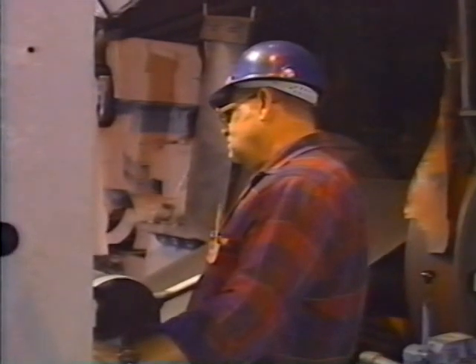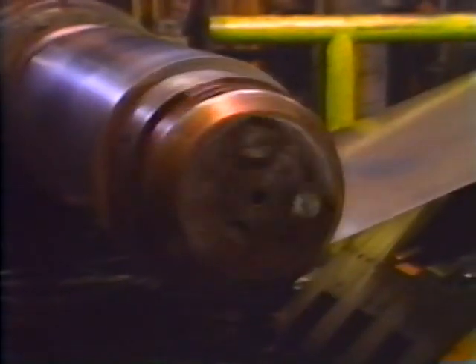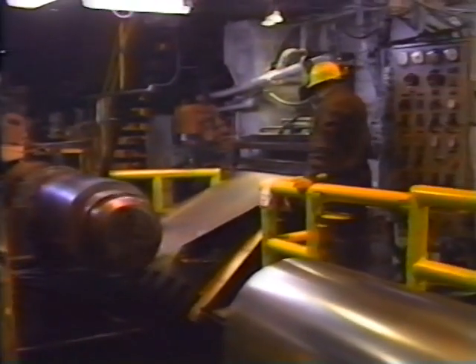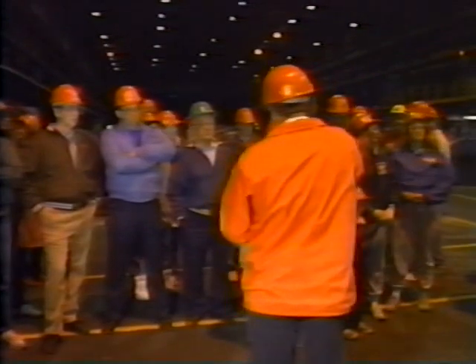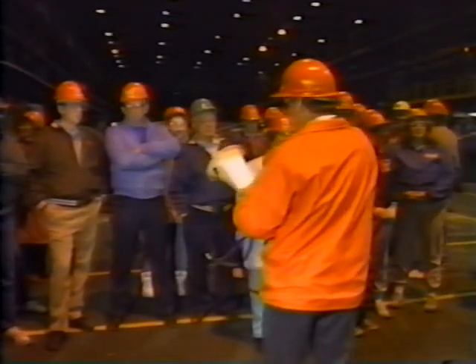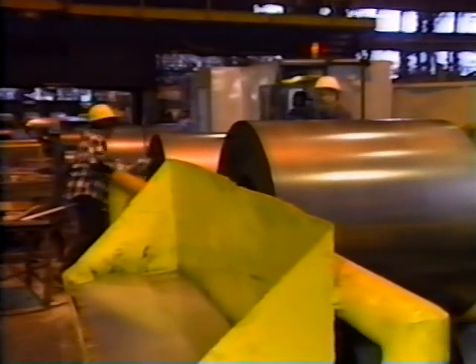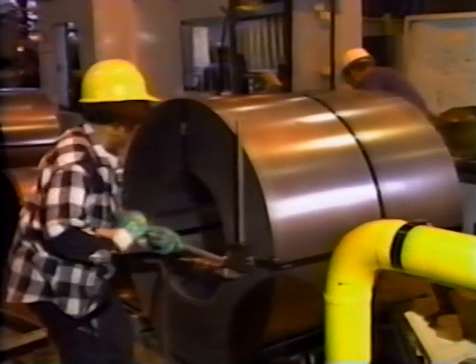As the steel passes through the 32-inch rolls, which exert enormous pressure on the steel, it reaches speeds up to 40 miles per hour. This final squeezing reduces the coil thickness by 1/2 to 1% and introduces the desired temper or hardness. From this point, most of the steel has been banded for the last time and is ready for shipment to the customer.